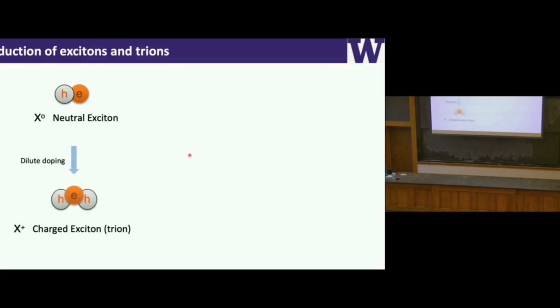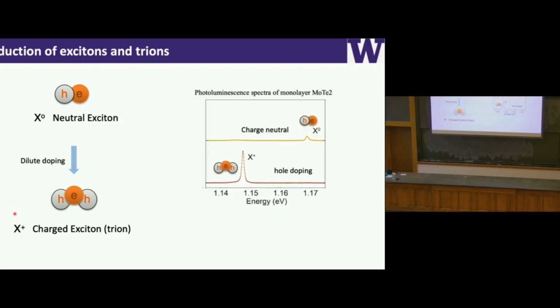Then I can start to dope the system. Imagine I dope holes into the system, and in a dilute doping, the screening is still weak enough. Then these excitons can bind to extra carriers to form a charged exciton, so we call them trions. Now here the trion is formed by 1 electron and 2 holes. So the trion will have a lower energy compared to the exciton because it's a bound state. And spectroscopically, we can tell them apart by looking at their energies.